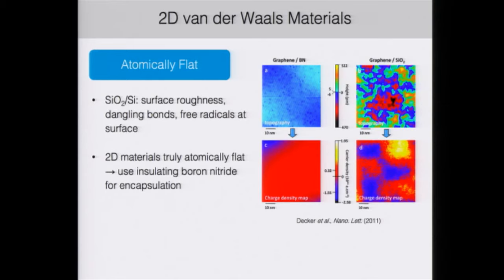When we say that 2D materials are atomically flat, we really do mean down to the atomic limit. If you take a conventional silicon wafer with a silicon oxide layer on it, there's actually quite a lot of surface roughness, as well as some dangling bonds and free radicals at the surface that can interfere with the device that you fabricate on top. In contrast, boron nitride, which is a very good 2D insulator, really is atomically flat and can screen some charge impurities and other things from the silicon oxide if you place a layer on the bottom below your graphene device.